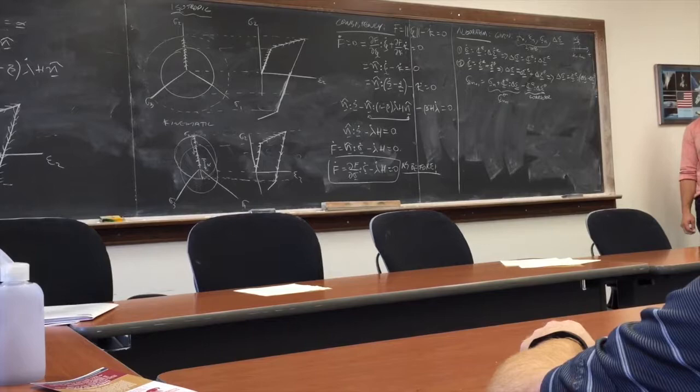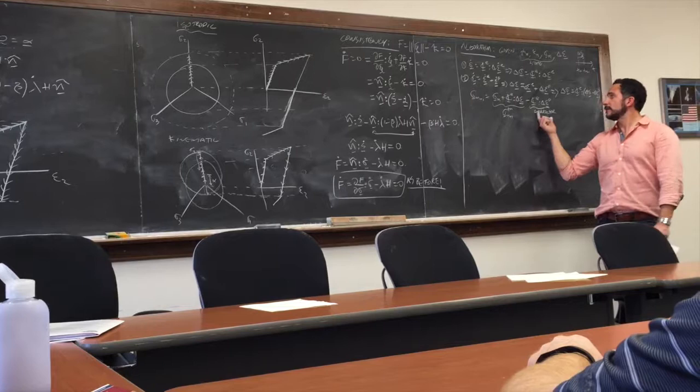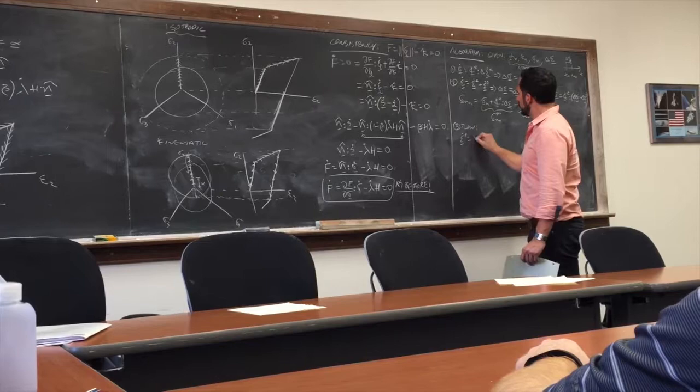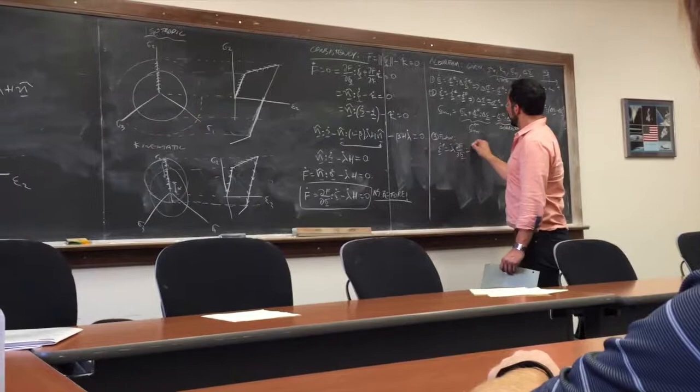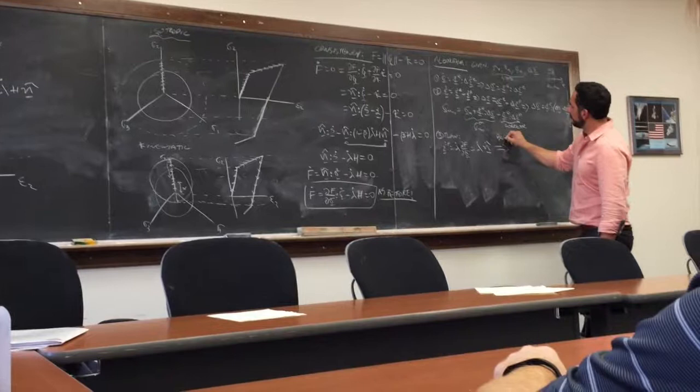Everything in the trial state is known. You know your elasticity, you know your state of stress before, you know the new increment in strain. You don't know the corrector yet. For that, you need the flow rule. Here you introduce your first approximation: backward or forward.